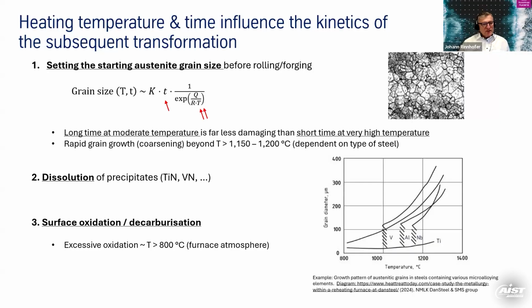Another topic is the dissolution of precipitates in the steel. You see this little diagram here. At high temperatures, some metals are dissolved in the steel structure, and also the grain diameter will grow when you heat for a long time. And another very well-known issue is the surface oxidation and also decarburization of the steel surface, which happens excessively at very high temperatures of more than 800 degrees. So you have to watch the furnace atmosphere, especially the oxygen content in the furnace atmosphere, which can be caused by false air, or by the combustion system when you have too much air in the burner system.